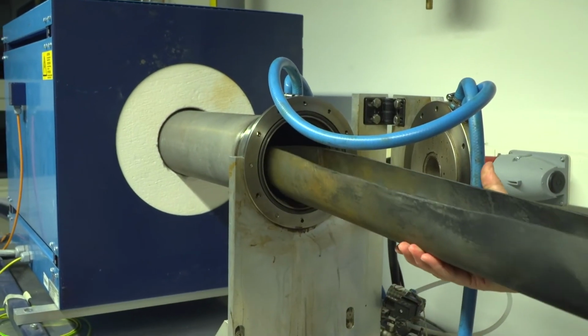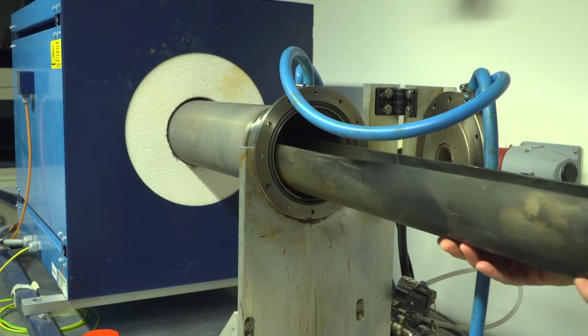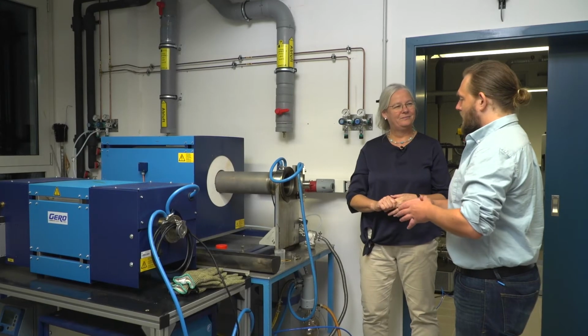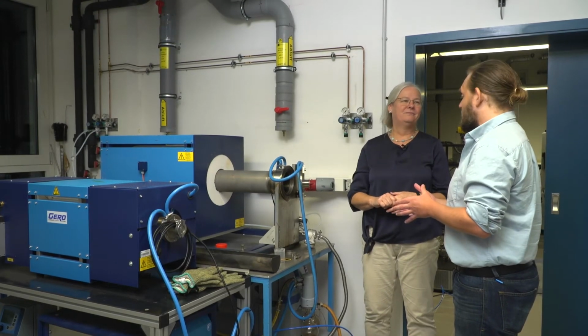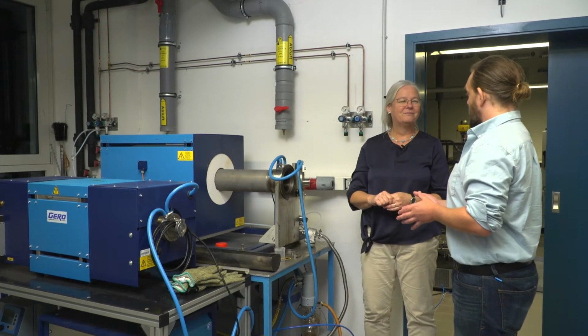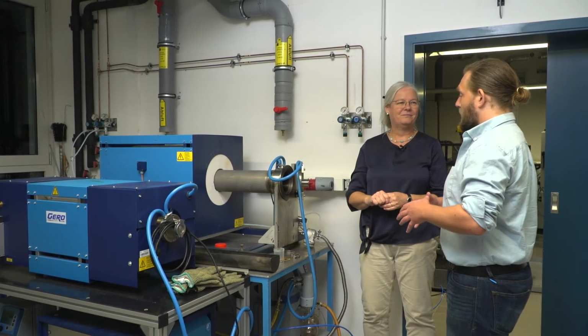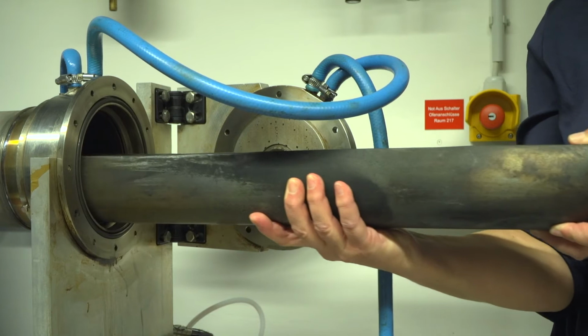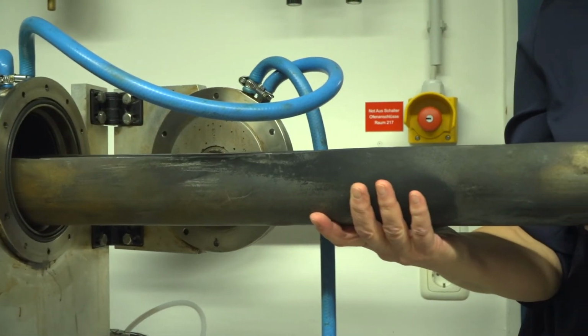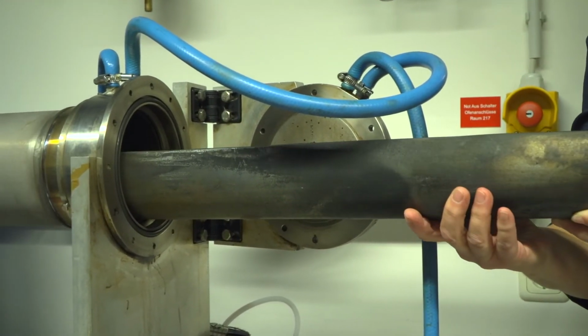1,000 degrees. This is a really cool technique because you can take a carbon aerogel that would otherwise have about 750 square meters per gram of surface area, and then make it like 3,000 square meters per gram. Yeah, we ended up with 3,500 even. 3,500. Wow, that's incredible.